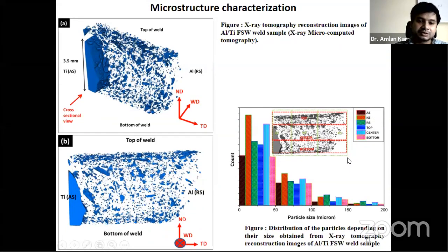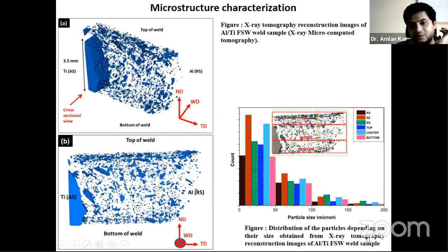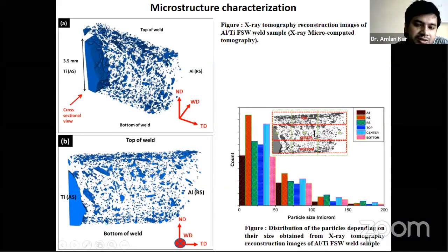And that is because of the deformations on the titanium side. You can see that at the top side you have a higher deformation in comparison to the bottom because of the shoulder affected region. Then we have seen different locations: this is the retreating side, this is the advancing side, and this is the top, and this is the bottom, to figure out the distribution.